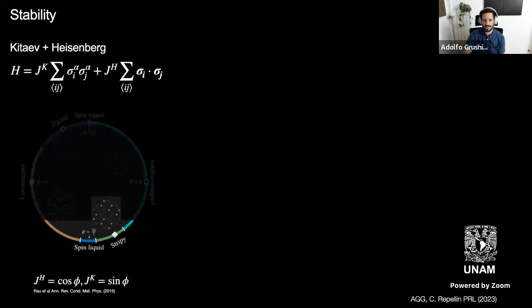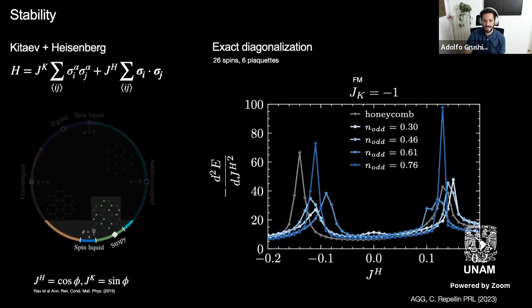And what we find, in fact, is that if we do exact diagonalization, the gray line is basically the crystal, and the blue lines are the amorphous, and essentially it's the same phase transition. It's at the same location in terms of this Heisenberg coupling. I'm not sure this answers your question, so please feel free to clarify what you mean by edge ferromagnetism. I guess the short answer is no: one of these phases is certainly a ferromagnet, and the other one we don't know. We haven't looked.